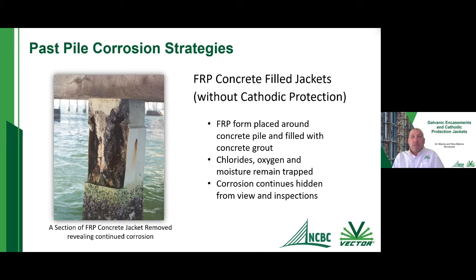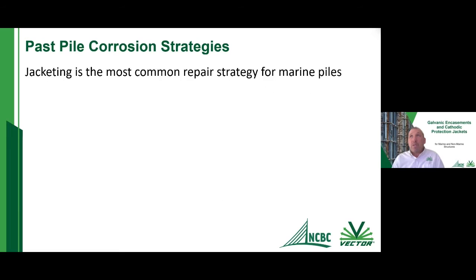And the bad thing about it is corrosion continues behind this jacket, and it's not visible when you come out to do an inspection. It can be fairly aggressive in here behind it before you actually see any sort of damage or delaminations to this fiberglass jacket as well. So jacketing is obviously the most common repair strategy that we come across when we're out there.